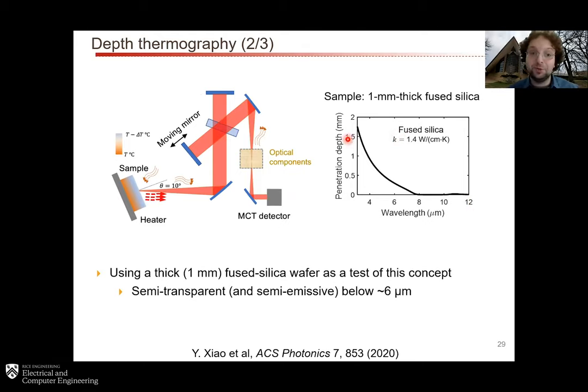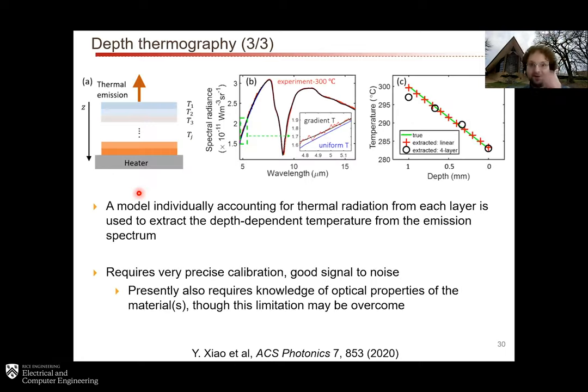It also has very low thermal conductivity, which means that if you put the sample on a heater stage, you are going to have a gradient of temperatures from the hot stage down here to the air up here. It's going to be colder up here by at least a few degrees if you have a 1 millimeter fused silica wafer, as I'll show you in just a second. So the idea here is just you put this sample on the heater and you measure the thermal emission, and then you try to invert that thermal emission spectrum to figure out what the underlying temperature distribution is. So here is how this works.